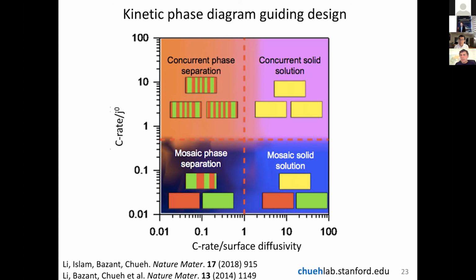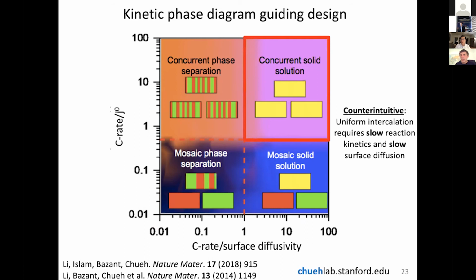So by embracing these design concepts, we can now pick our optimal design space. And it's very counterintuitive. It tells you that in order to have uniformity, you need to have slow kinetics and you need to have a slow surface diffusion coefficient. And this is something that has not been realized for this material, but this is the design space which can give you very uniform intercalation. If you go to the diagonal on the bottom, where you have very low resistance and very high surface diffusion, then you have the situation that the material is extremely heterogeneous, both within individual particles and in the population.